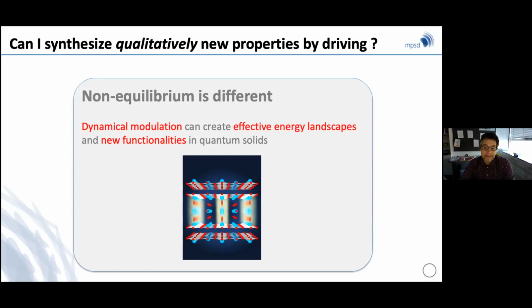So we will think about a material in which a light pulse modulates the Hamiltonian in time, and we will ask, what are the low energy effective properties that average out these fluctuations, the drive, that are sampled at frequency slow compared to the periodic drive, and how can I think about this? So there's a drawing there that is a caricature of a cuprate superconductor in which a specific phonon, in this case, the phonon that modulates the distance between a certain oxygen atom and the superconducting planes, is being modulated in time to large amplitudes.